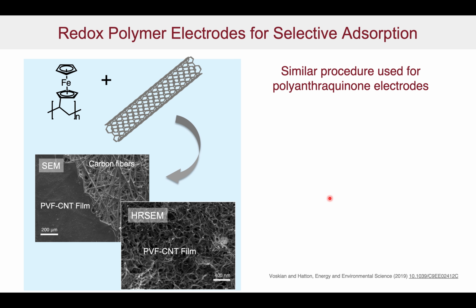Now, the way in which you prepare these electrodes is quite straightforward. We take the polymer, in this case the ferrocene, but also the same for the polyanthraquinone, wrap it around carbon nanotubes and put them in a suitable solvent, and then use that solvent ink to either drop cast or dip coat carbon fiber electrode substrates. You can see from very close up that the film that's formed is very, very porous. These are the carbon nanotubes, and they're coated with the polymer.